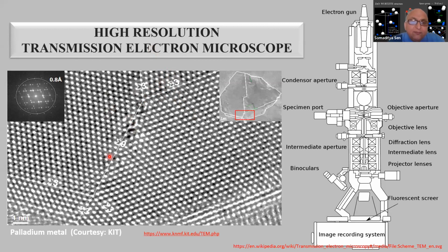Okay, so you can see when this type of crystallographic reorientation has taken place, there is often a region where there is some turbulence in the regularity of the material. This type of information can be obtained from HRTEM, high resolution transmission electron microscopy. Obviously, the EDX can also be done. What we can do is take a specific area where the regularity is there and Fourier transform the data, and we can get a diffraction pattern like this. This is a typical Laue type diffraction pattern as we obtain from X-ray diffraction. We can do a similar analysis on electron diffraction too. This is called selected area diffraction in the electron microscopy system.